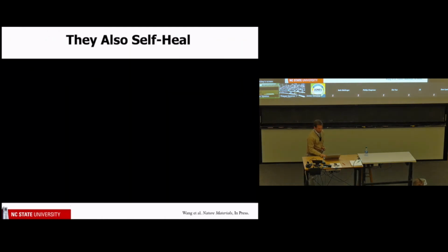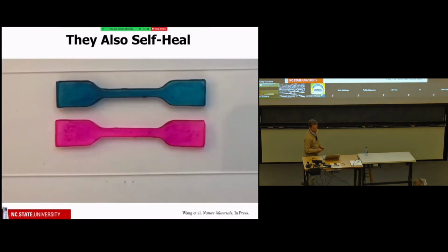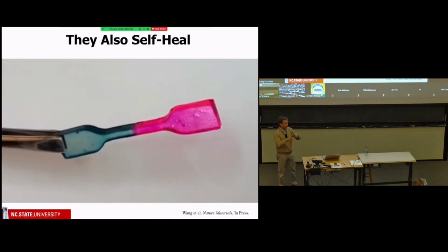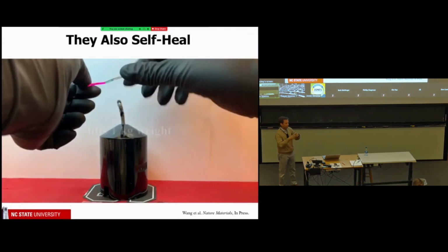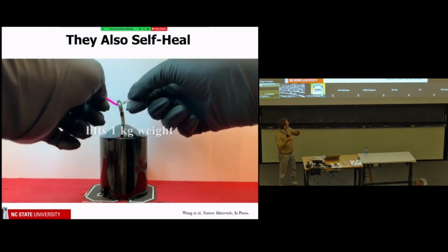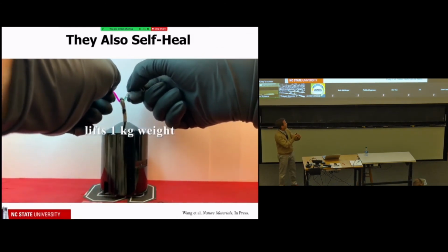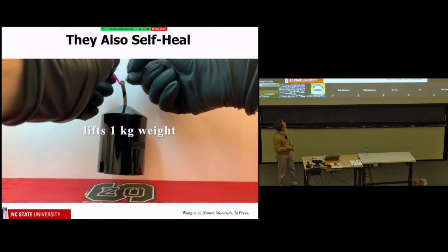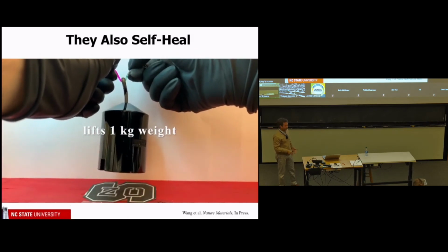And, kind of neat, they also can heal. So when you cut these two things and put them back together, those little domains that I described to you, when you heat them, they become solvated, and then when you cool it back down, they lock the interface together. So it requires heat, but you can get this to heal.